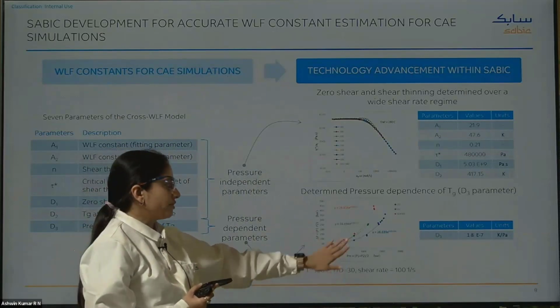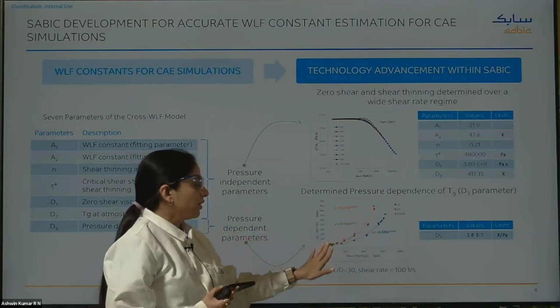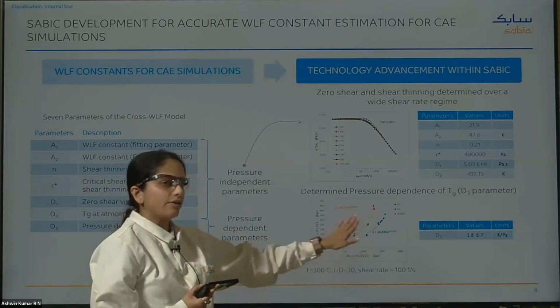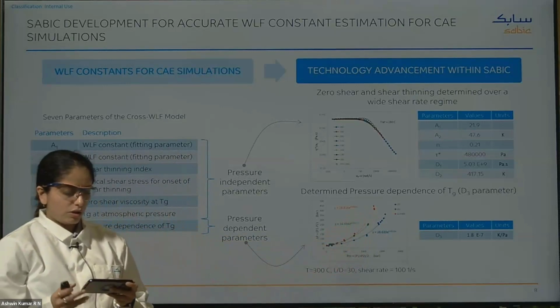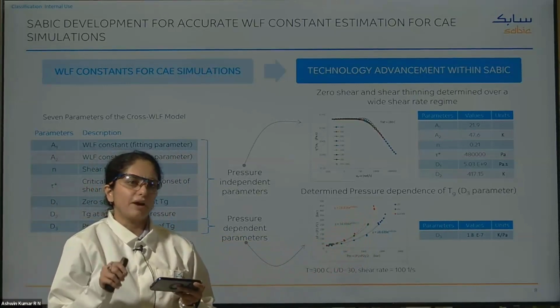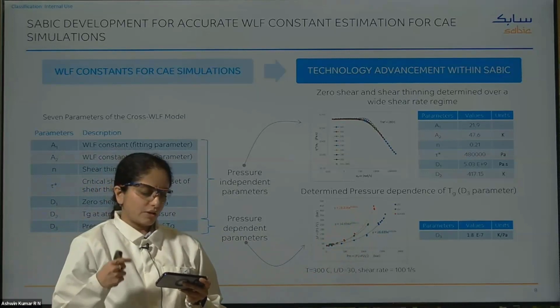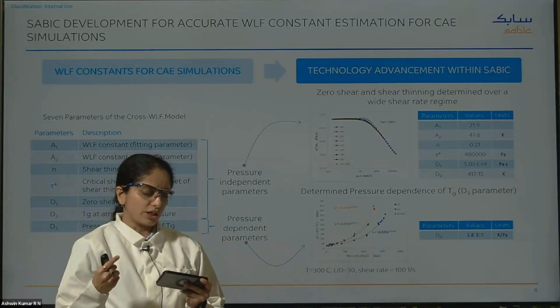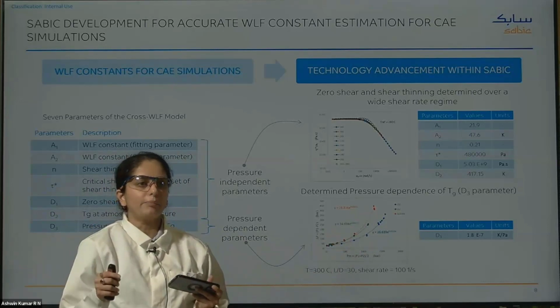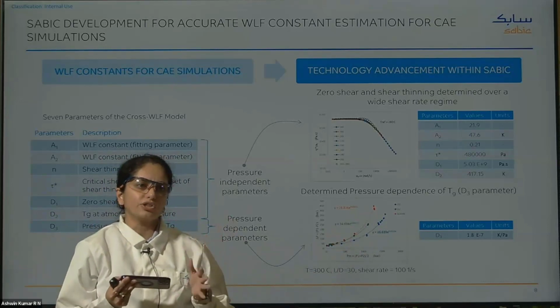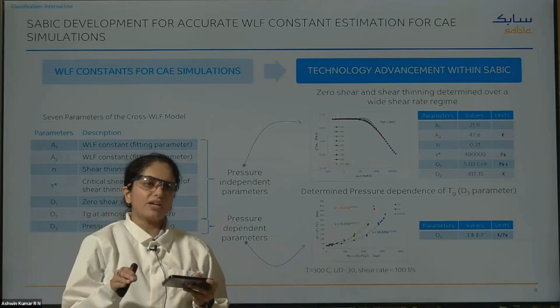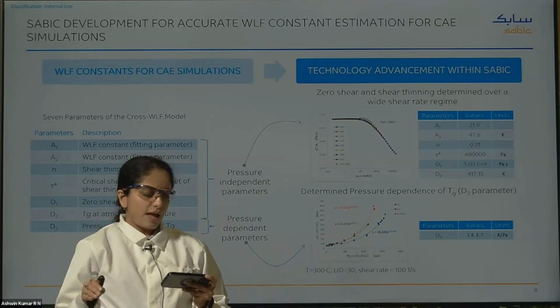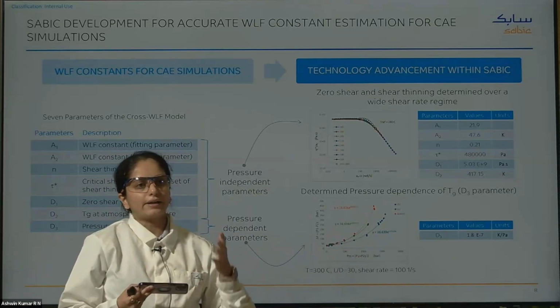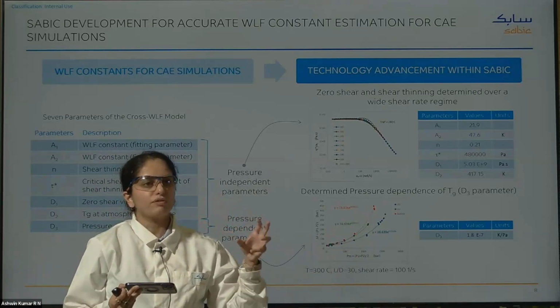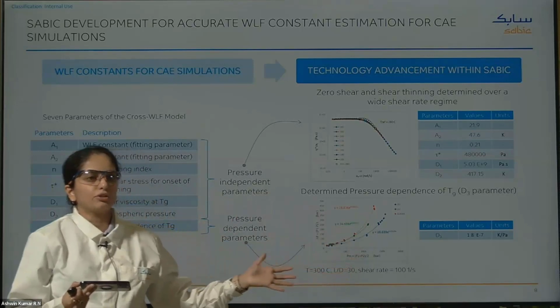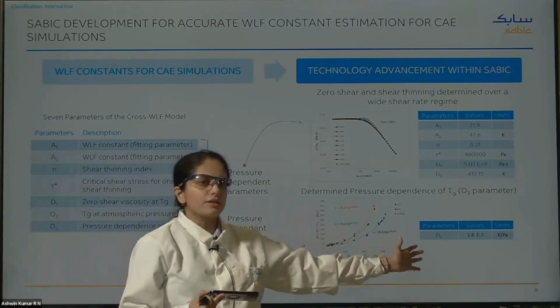versus the average pressure. And we see that the melt viscosity is influenced by pressure. So it goes on rising continuously. So we have this counter pressure measurement device wherein we capture the influence of pressure on viscosity, and this is done at a constant shear rate of 100 per second, which is in the Newtonian region of the polymer melt. And this is applicable for the amorphous polymers as well. And then we can characterize our pressure dependence coefficient beta, which leads us to the calculation of D3 parameter, which is given in this slide here.